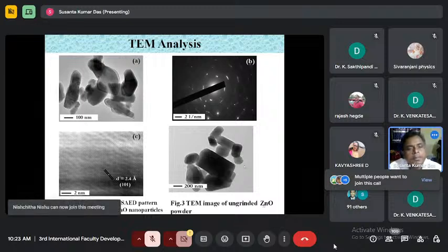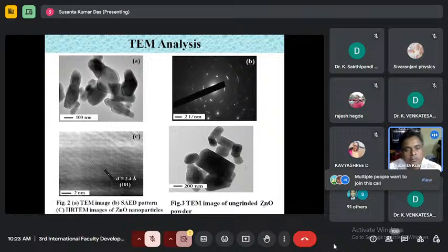This is an advanced study, you know. So we have seen that ungrinded is much larger, around 200 nanometer, whereas grinded are much smaller, below 100 nanometer, which is now qualifying to be called nanomaterials, because for a material to be called nanomaterial, its dimension has to be less than 100 nanometer. Then we had gone into that regime, and it was verified through this also.